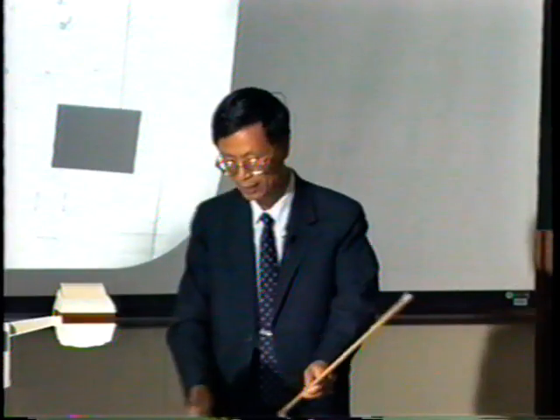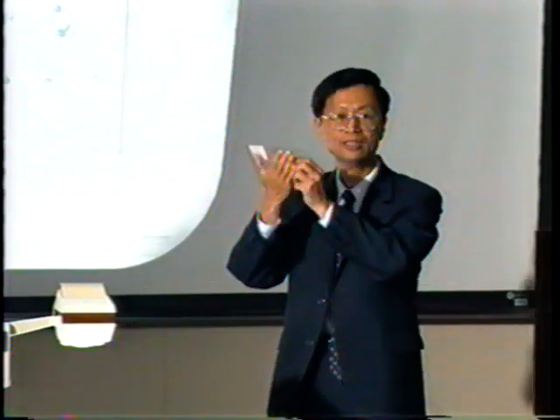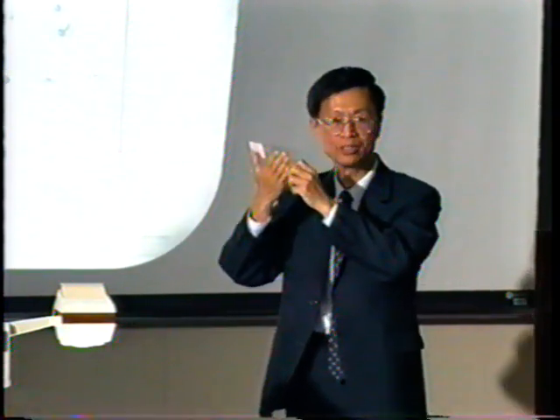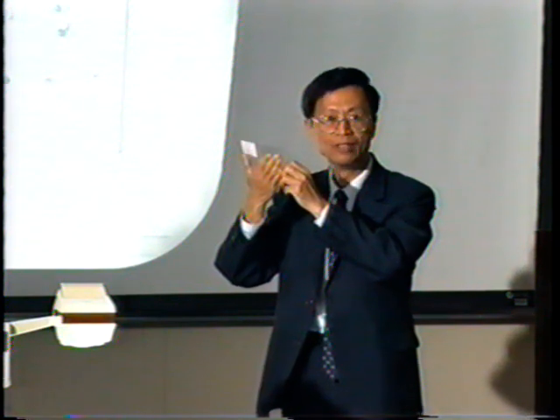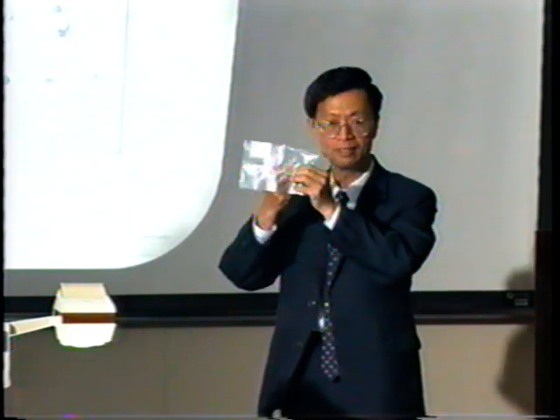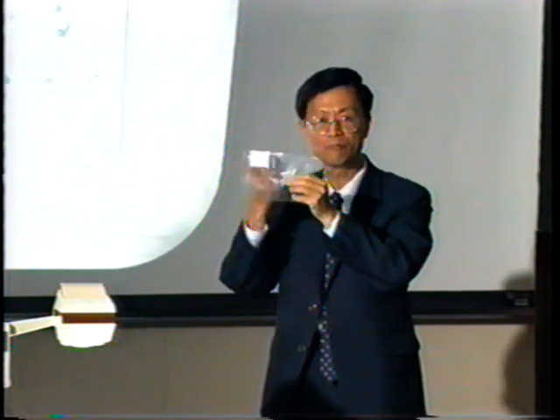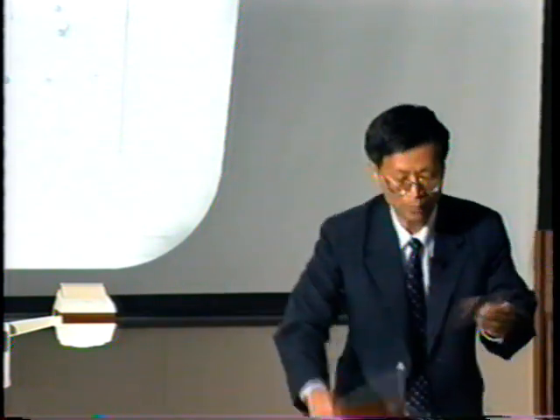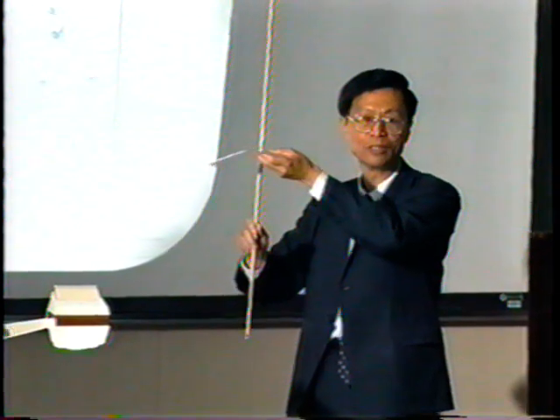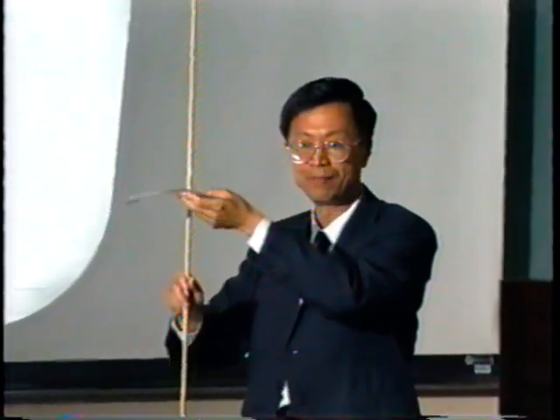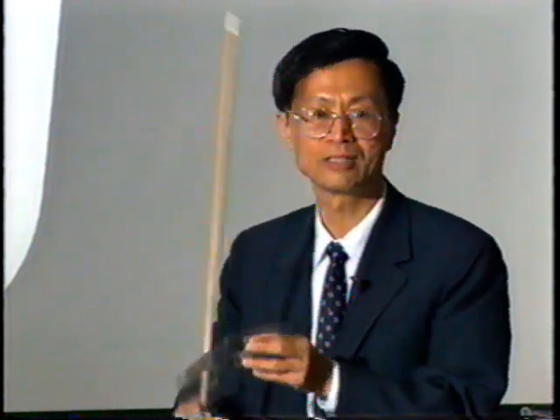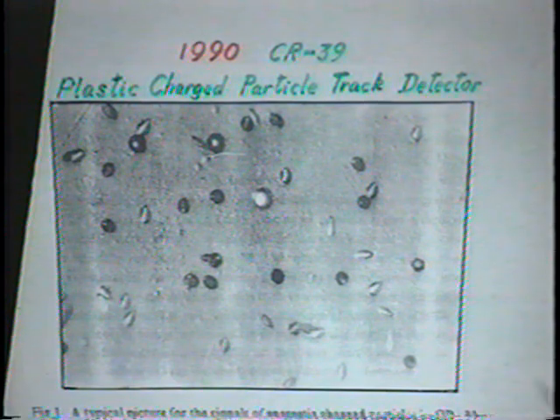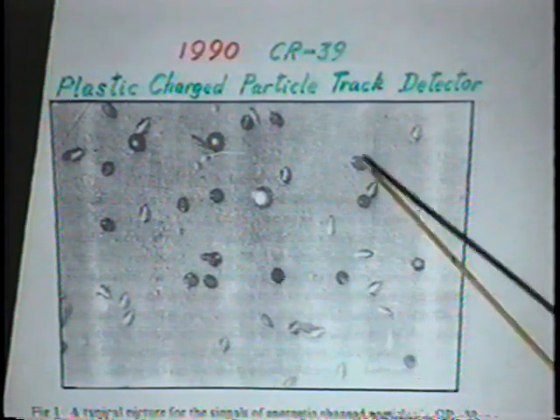If we put this plastic with a palladium sheet and we load the palladium sheet with deuterium or hydrogen, then we will test whether there is any energetic charged particle from the surface. When the charged particle penetrates these plastics, it will create a damage. Then we put this in the chemicals. The etching process will create a pit along this damage.